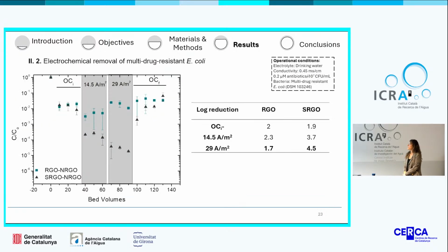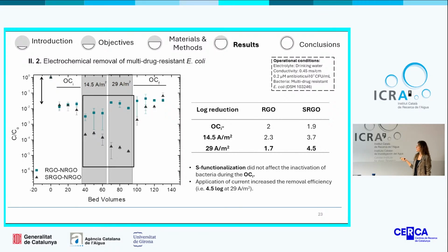The electrochemical removal of a multidrug-resistant E. coli is presented in this slide. According to this result, we could observe that during the open circuit conditions, S-functionalization did not affect the inactivation of bacteria. However, we achieved almost two-log removal, probably a consequence of the membrane stress created by the direct contact of the bacteria with the nanosheets of our electrode.